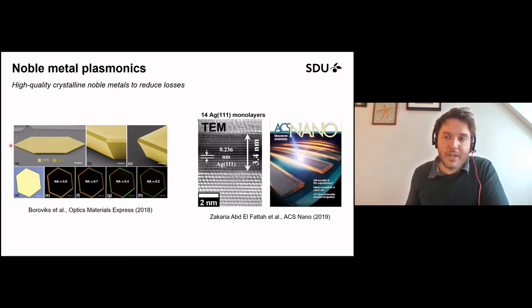So this is something we actually have access to at SDU, and there's been a lot of experimental research in this area. And actually in my former group at ICFO, they've also been looking at crystalline noble metals and making them incredibly thin, just down to a few atomic planes of thickness, right? We're talking about 14 monolayers of silver in this case, with a very well-defined crystallographic orientation. So these are kind of state-of-the-art noble metal materials for plasmonics that are starting to attract interest just in the last few years, and they're becoming more widely accessible.